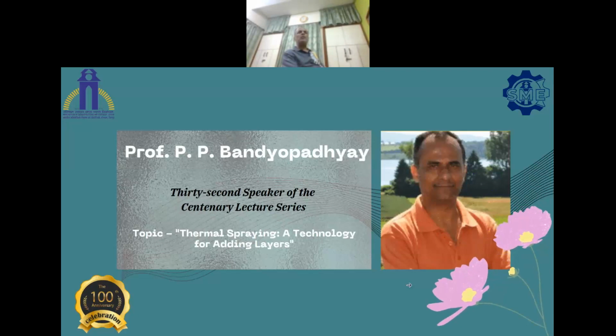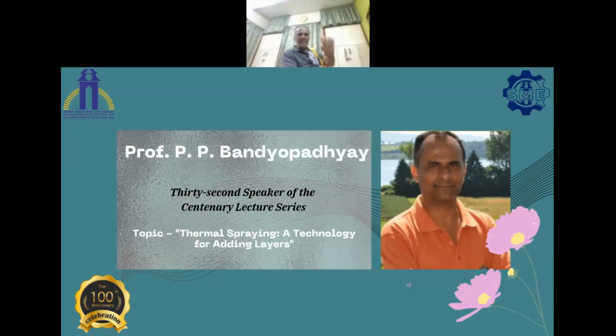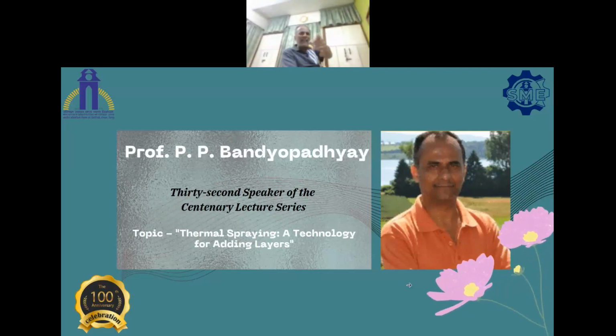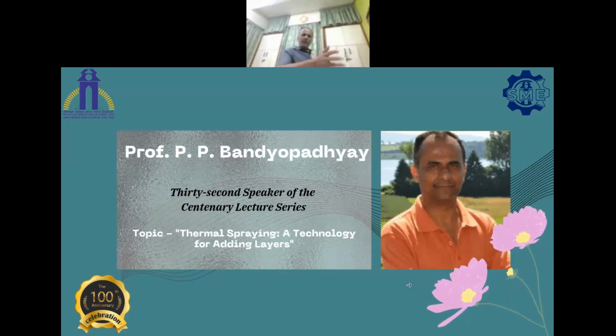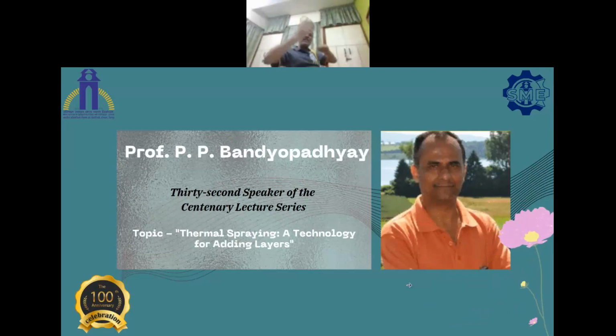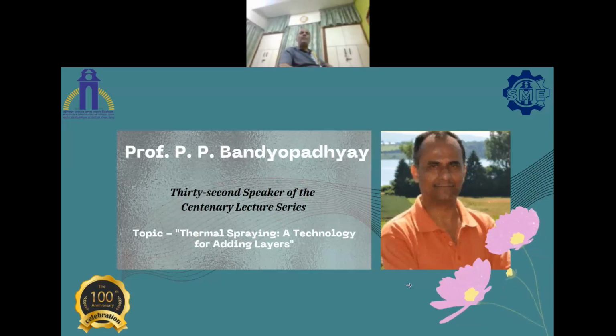I had the opportunity to do some vacuum-based processing. I shouldn't call it vacuum. You evacuate the chamber, then put in some gas at low pressure. You have to constrain the flame. In vacuum, the flame travels very far. But if you put in nitrogen and argon, you can keep oxygen away and you can constrain the flame as well. Whatever work in vacuum plasma spray or low pressure plasma spray I have done, I did it abroad. I didn't get a chance to do it in India.